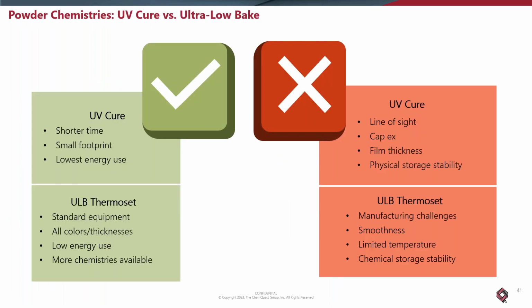So if we want to summarize things here, UV cure versus a thermoset ultra low bake. UV cure gives you a lower temperature, shorter cure time, small footprint. The thing about ultra low bake thermosets, they're easy to pigment. The film thickness is not going to be critical. It's relatively low energy use. The equipment's more standard. It's an easier jump to go from traditional standard baked powder coatings to a fast cure or a low temperature cure thermoset.